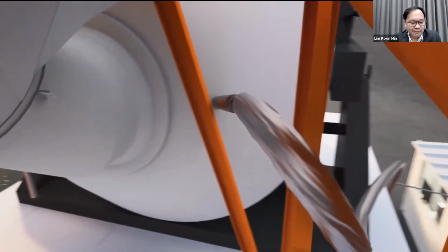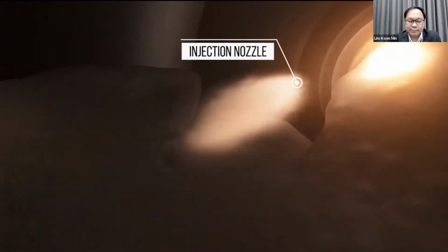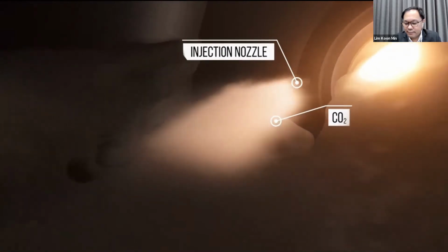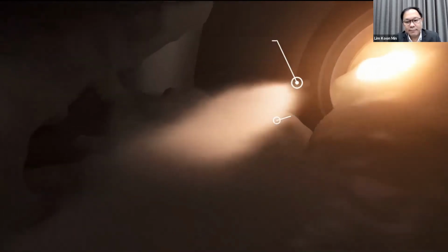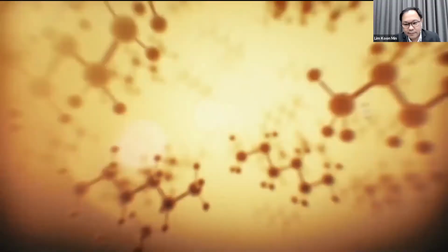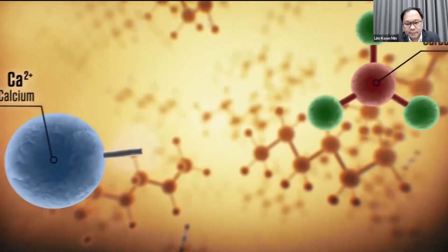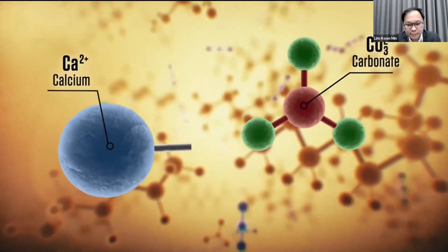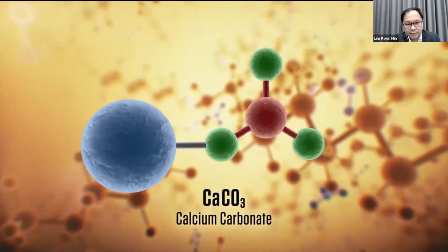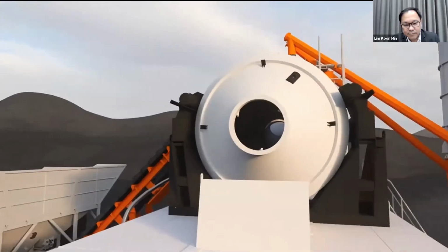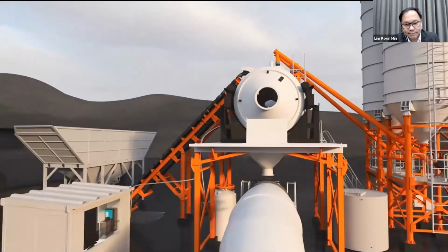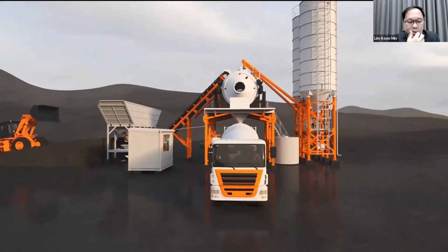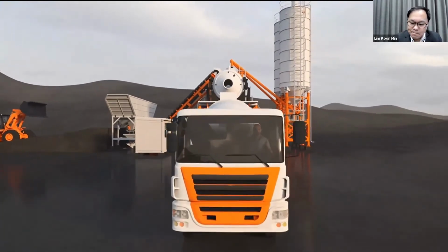While liquid CO2 is stored in the tank on site, the CO2 that comes into contact with the concrete is actually in a solid and gaseous state, similar to dry ice or snow. It changes state once it leaves the Carboncure valve box due to a significant drop in pressure. Upon contact with the mix, the CO2 undergoes a chemical reaction and converts into a mineral, calcium carbonate, which makes the concrete stronger. Plus, what was once CO2 is now eliminated, never to be re-released into the atmosphere, even if the concrete structure is demolished.